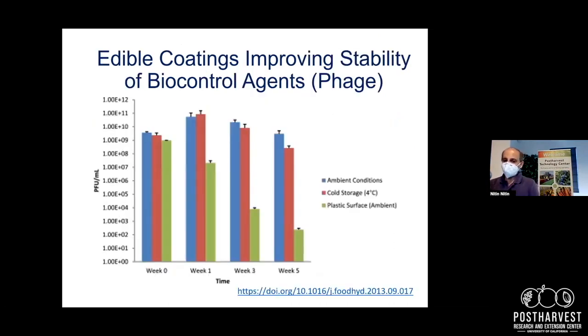So we had done some study before where we had looked at how edible coatings could improve the stability of biocontrol agents during storage. And as you can see, without the coating, you lose a significant amount of activity. And this is on a log scale. So you're not losing activity on a linear scale, you're actually losing activity on a log scale. So losing 5 log means that you have lost 10 to the power 5-fold activity of your agent. By using some of these edible coatings, we were able to stabilize these phages on different surfaces, including plastics, and they could work in ambient and storage conditions.